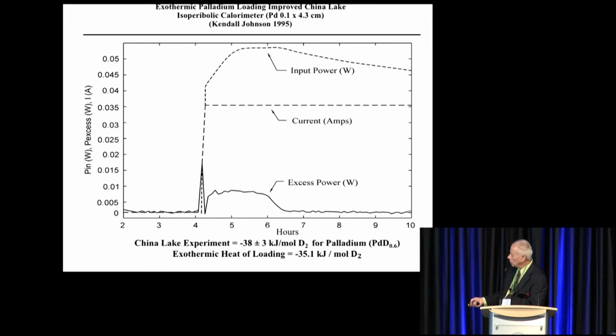And my analysis gives you minus 38 kilojoules per mole of deuterium. Now this number depends on what you're relating it to. Moles of deuterium, not moles of palladium, because that'll give you a different number. They're both right, but they're different. And the literature value, if you base it on moles of deuterium up to 0.6 loading, is minus 35.1 kilojoules per mole, and we're within the error limit of that experiment.